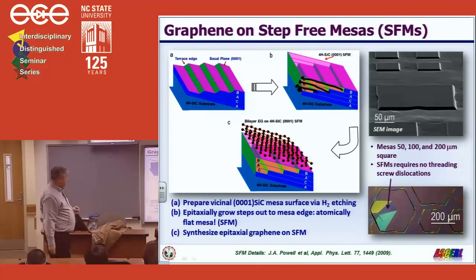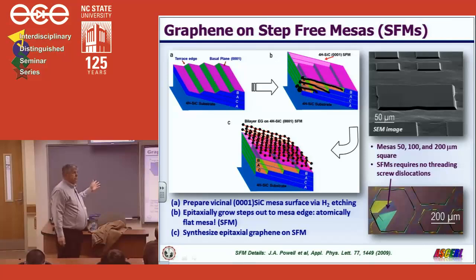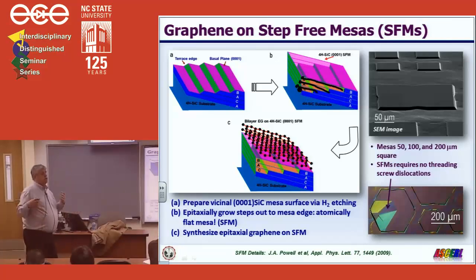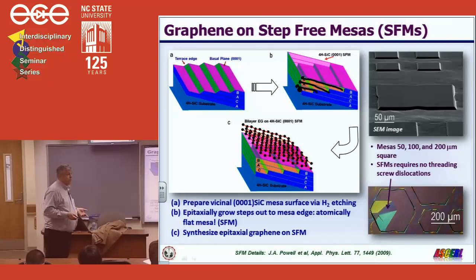Here's an SEM image on the top, and you don't see any imperfections at all. And we also use ECCI, and we saw nothing. It's flat. It looks like Iowa. On the bottom, this is a mesa that has a screw dislocation. And even in a Nomarski microscope, you can easily see the imperfection. So there will be a small number of mesas that will be perfectly flat because they don't have a screw dislocation.